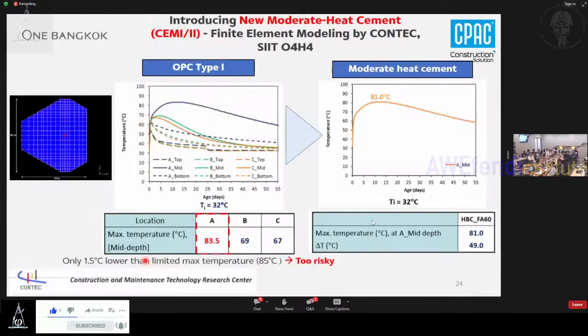We have all aspects together to combine as a model, and after that, we calculate the structure. What is the tensile strain that's going to happen at the structure? After that, we put the rebar to control the crack. This is the overall, quite very excellent work from SIIT.